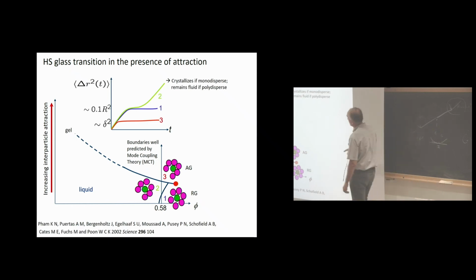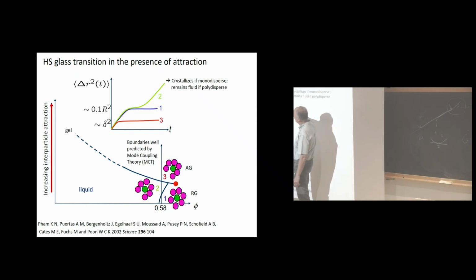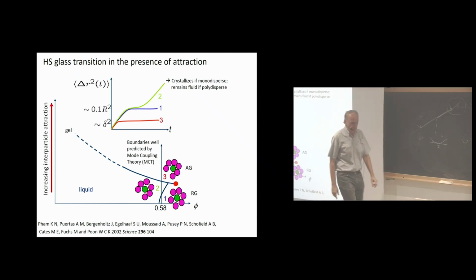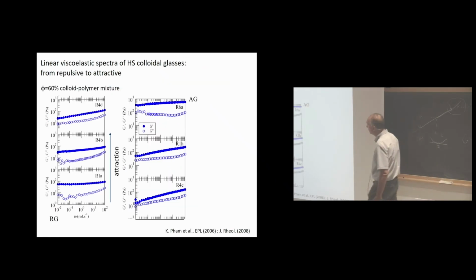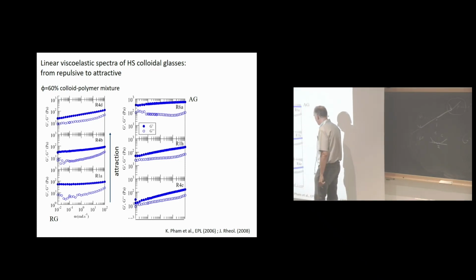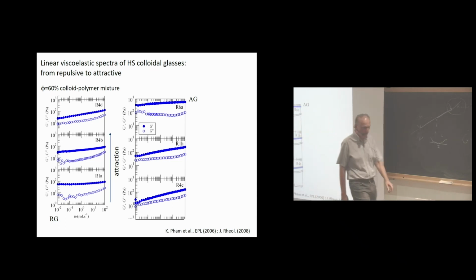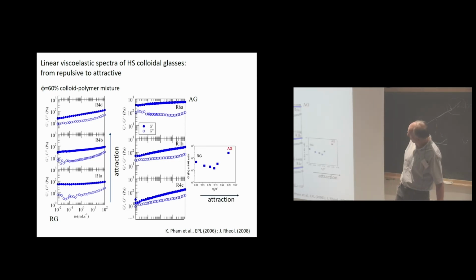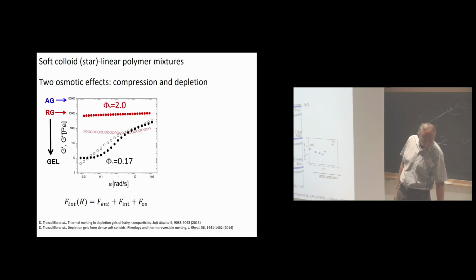Okay, I'll show you here mean square displacement, right? This is the classic repulsive glass. Okay, the attractive glass has, of course, a smaller mean square displacement, and of course, the liquid flows. And this is finishing up. If you do linear rheology, so you start basically from repulsive glass. This is G prime and G double prime around 100 Pascal. You increase attraction this way, and then this way up, and you increase the modulus in the system, whereas more or less the rest is pretty much the same, except that the G double prime has a slightly different shape. And I think this is it. You see how the modulus now changes as function of the effective concentration of the star.